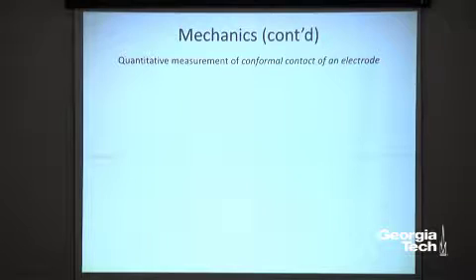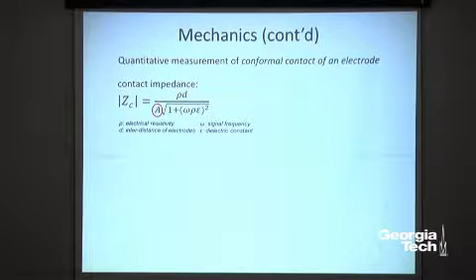We can also do quantitative measurement, right, in terms of electrical signal. So we could measure this contact impedance between skin and electrode. And based on this equation, the contact impedance is inversely proportional to the contact area. Here, A, right? Then if contact area increases, your overall impedance decreases. Right? So when you compare two different cases where you have nice contact of your electrode versus poor contact of your electrode, nice contact of your electrode can give you a larger contact area, right? So that's something we want to measure here.